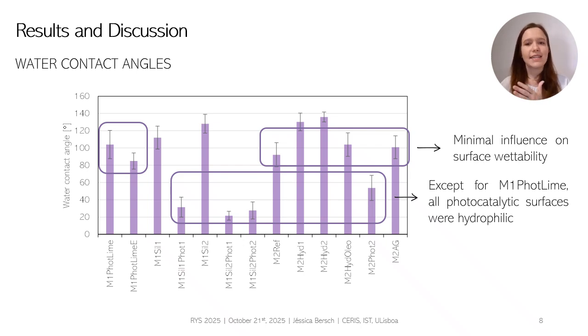Here, we can see water contact angle results, which are related to surface wettability. We consider 90 degrees as a threshold between hydrophilic and hydrophobic surfaces, those with results higher than 90 being considered hydrophobic. Firstly, if we look at mortar 2, we can see that the application of a hydrophobic and oleophobic coating or an anti-graffiti coating generated minimal influence on surface wettability compared with the reference specimen's uncoated mortar. Now, looking at the photocatalytic surfaces, except for the lime-based photocatalytic paint applied on mortar 1, all the other photocatalytic surfaces were hydrophilic, even with this test carried out without previous exposure to UV light.